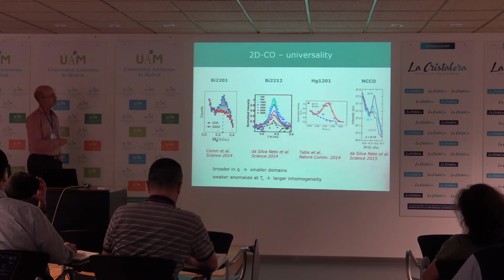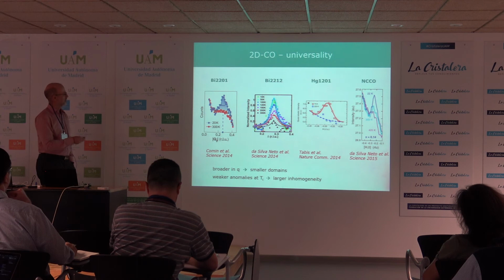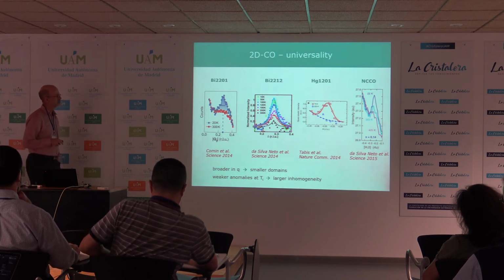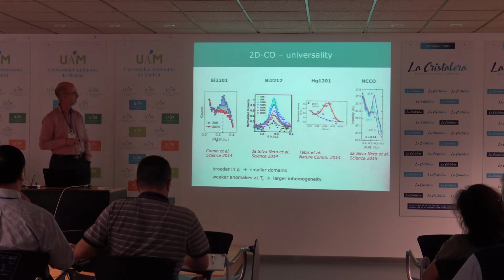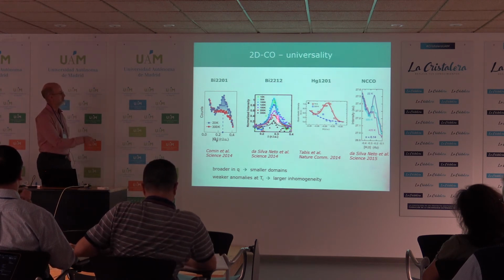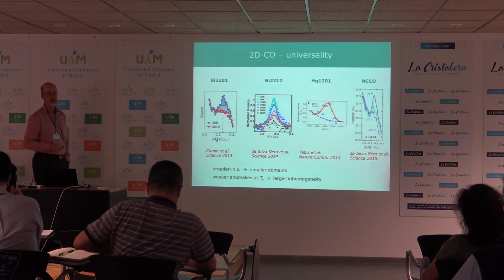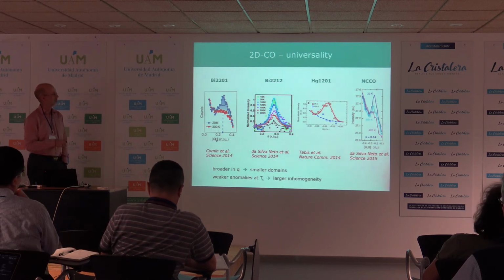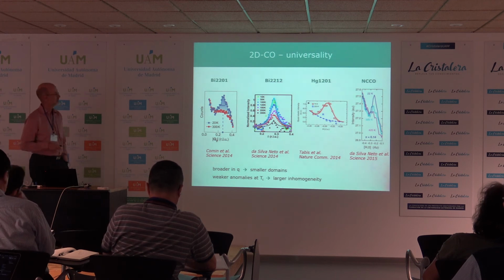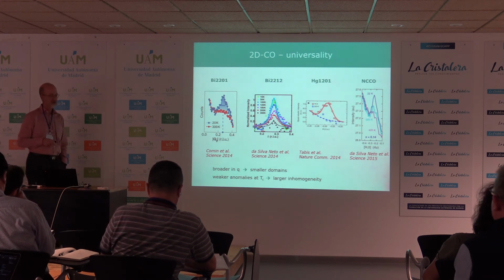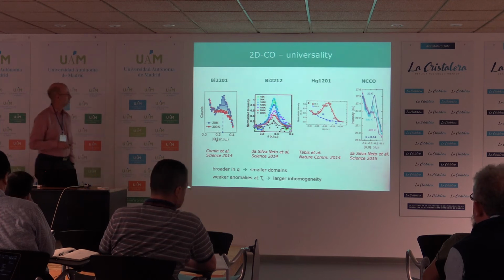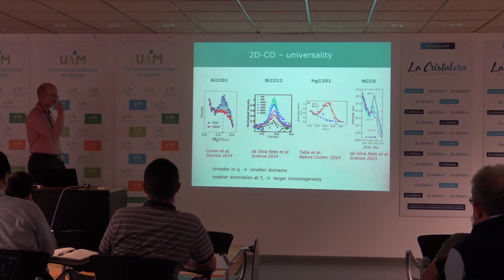Okay, now following up on this work, basically all families, even the electron-doped materials, have been investigated by resonant X-ray scattering. And you see charge order all around this wave vector, in all of these materials. So this is really a universal feature of the copper-oxides, and they're all in the same direction, always in the copper-oxide bond direction. But the width of these peaks differs quite strongly from one material to the other.